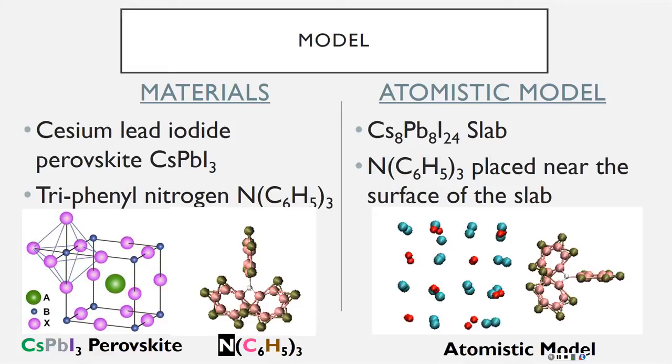In solar cells, can you use N and N or P and P doped silicon, or you need an interface? You need some sort of interface to produce the electric field to separate the charges. Can you make connections to this? So in this case, even though the cesium is charged, it doesn't create an electric field like the methyl ammonium would, because it can rotate and create little ferroelectric highways for the charges to separate. So in this one, there's no net internal electric field to separate the charges. So we need another molecule to pull one of the charges away.